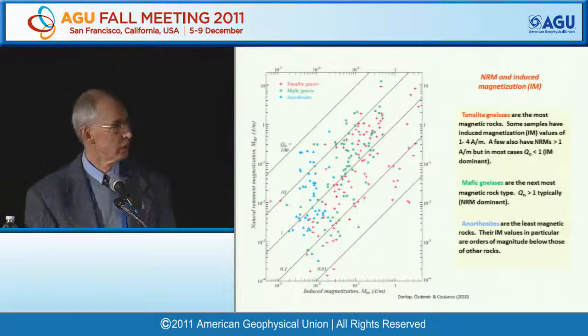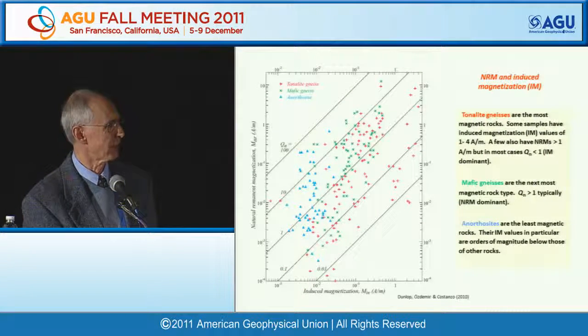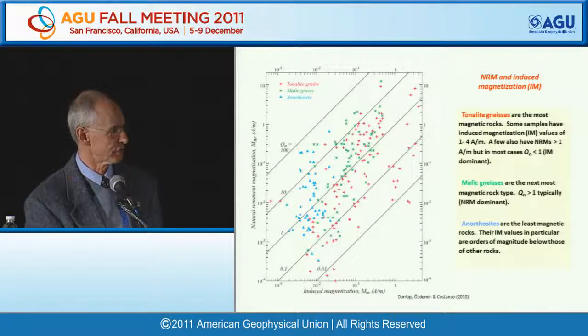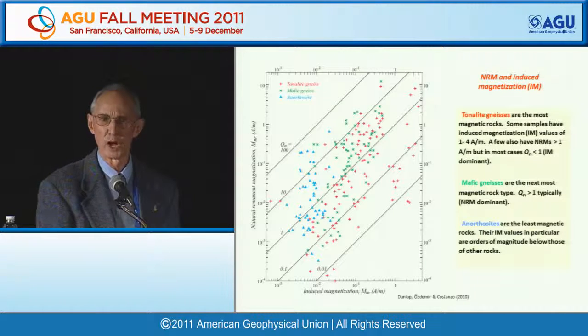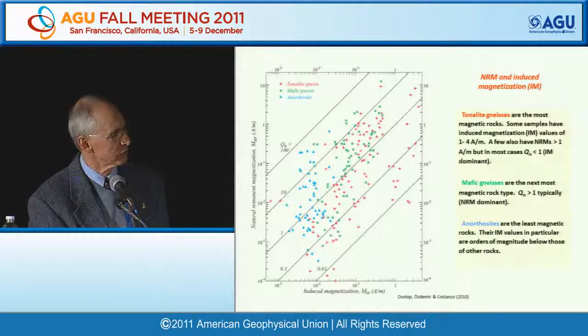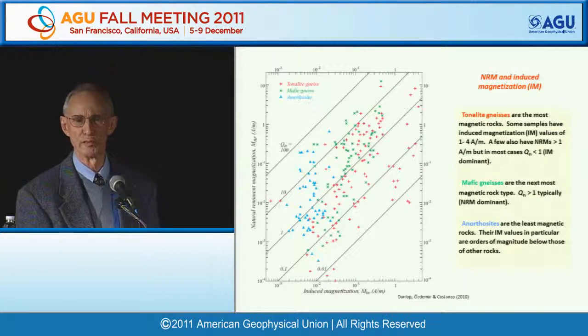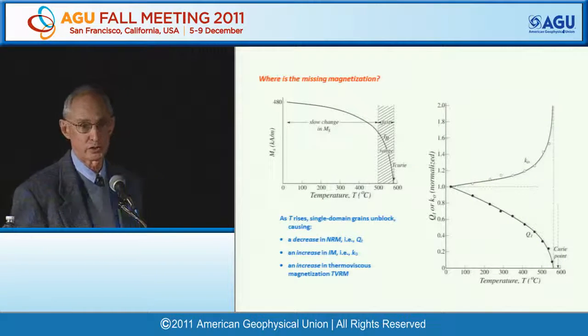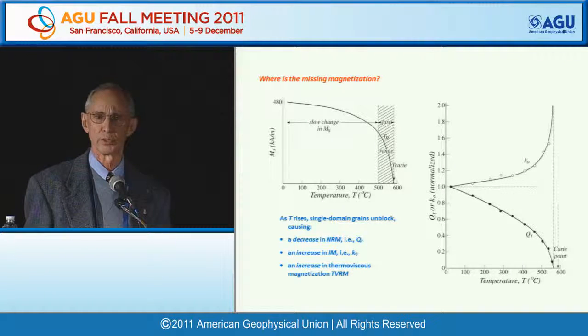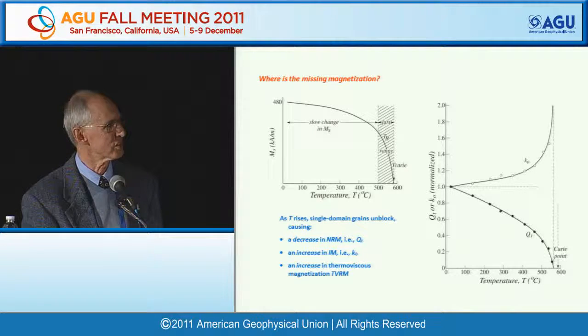And when you look at all the different rock types plotted here on this diagram that I like very much of NRM versus induced magnetization with the Königsberger ratio Q as a parameter, roughly speaking, everything above the middle line is remanence dominated, everything below is dominated by induced magnetization. The samples that would explain the anomalies are just up in this corner here, and there are very few of them. So the things we are seeing at the surface, which, remember, came from depth originally, so they are representative at least of some of the deep rocks, they don't have enough magnetization. Where is the missing magnetization?